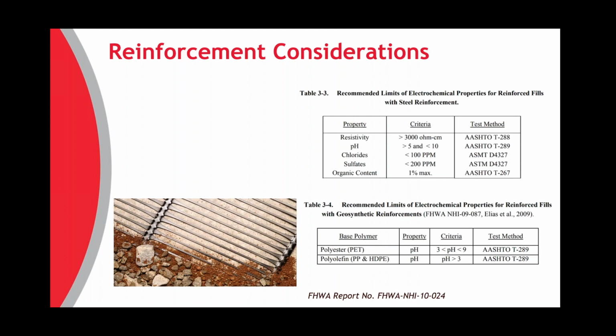Now, reinforcement considerations. We looked at this earlier about the electrochemical properties, and I mentioned pH is a major concern for soil reinforcement. 5 to 10 if you're using steel, 3 to 9 for polyester, and polypropylene and HDPE anything over 3. So typical pH values of recycled concrete is greater than 11. Coal combustion products can be up to 13. So that essentially eliminates steel as a soil reinforcement option, and essentially eliminates polyesters. So you're left with polypropylene and HDPE for these types of applications. So that's a very important consideration when you're designing structures using these types of backfills.